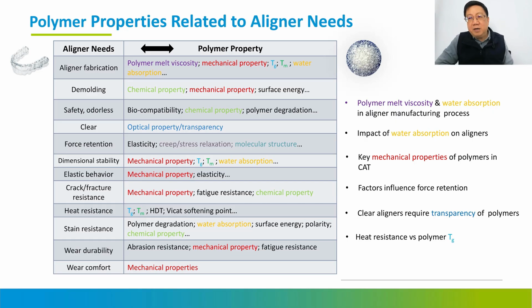But when you wear it, the key is that a single layer, as I said earlier, will decay so fast. Normally, in 2 or 3 days, they will decay by more than 60 to 70%. But if you use a good multi-layer with good elasticity, it can still keep about 70% performance. So it's nothing related to higher force to drive the teeth faster. It's related to continuous and comfortable force to move the teeth. So based on this, we can go into more detail later.